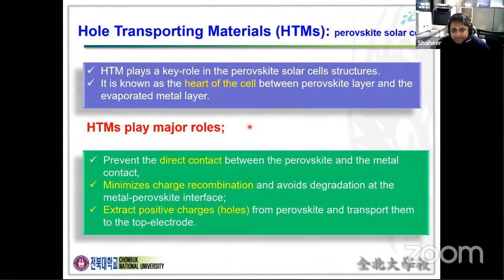So the first part of my talk, I will show you some of my laboratory work. Hole transporting materials are the key materials, or key layer, in the perovskite solar cell. That's why we call the HTM, hole transporting material, the heart of the cell. The main role of the HTM is to prevent the direct contact between the perovskite and metal layer, minimize the charge recombination, avoid the degradation at the metal perovskite interface, and also extract the positive charges, that is the holes, from the perovskite and transport them to the top electrode, meaning the metal layer.